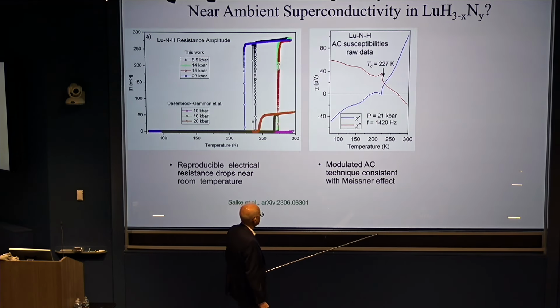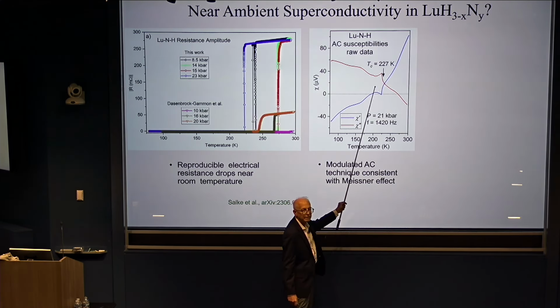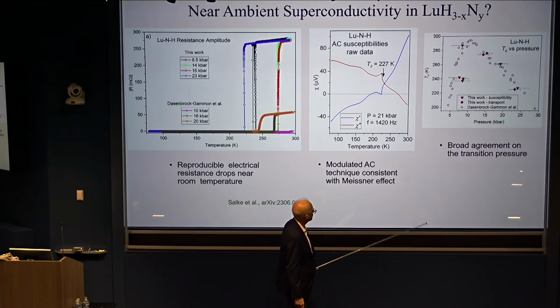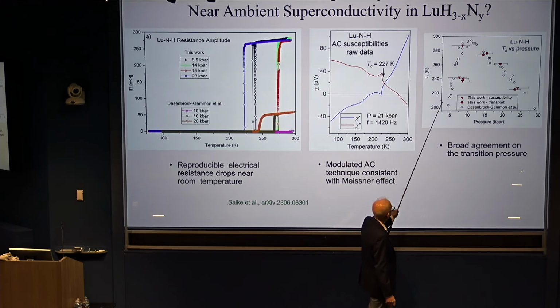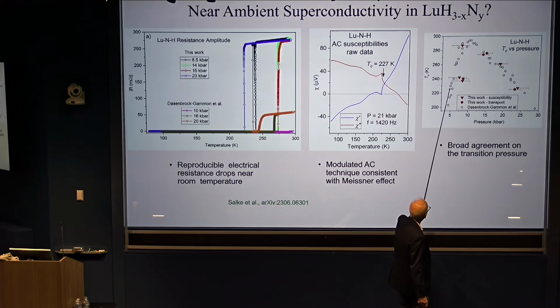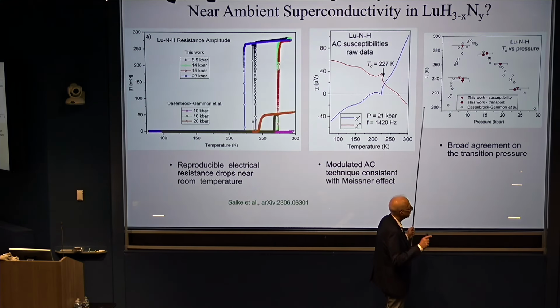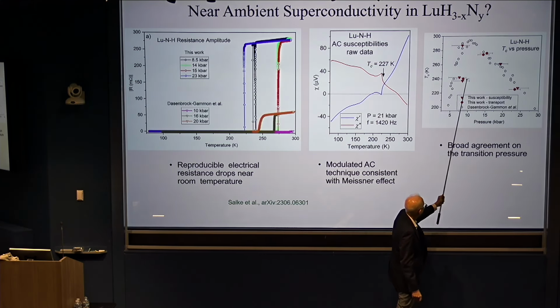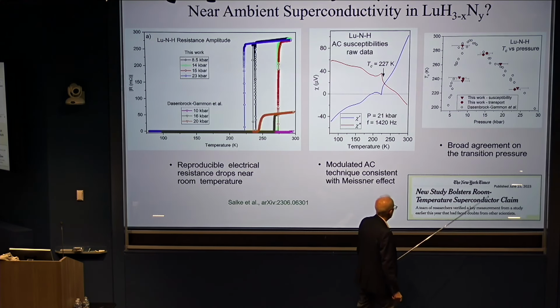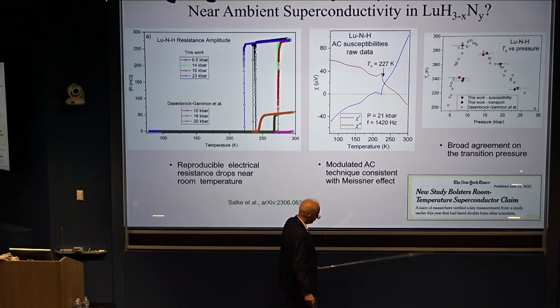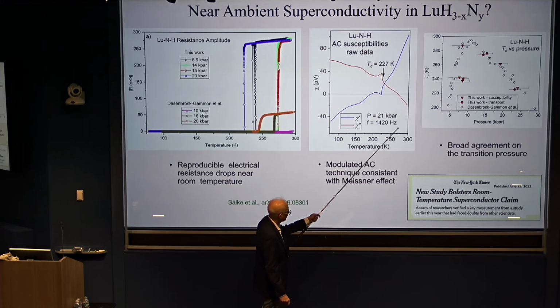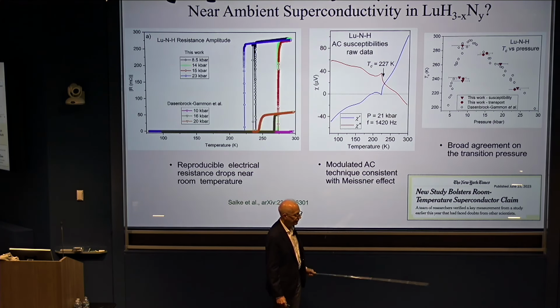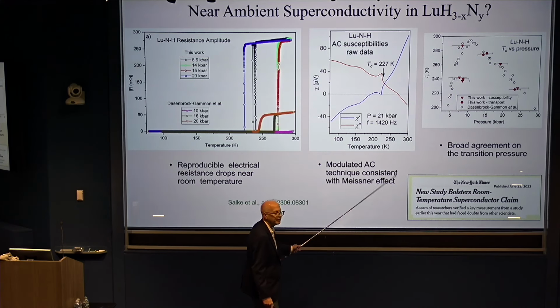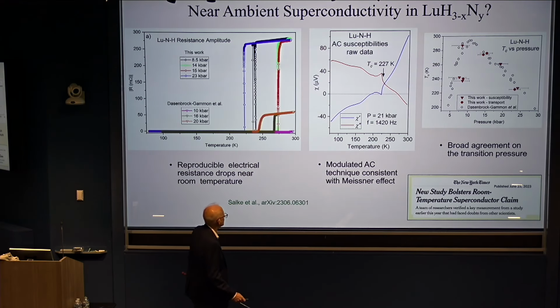We've also done magnetic susceptibility measurements, very similar to what we did for sulfur years ago, and studied a lot of other materials and see quite similar behavior. So if we plot all of this data together, we see a very similar picture of the variation in superconducting temperature, or at least some kind of critical temperature, versus pressure, now again, at quite low pressure. And this was quite exciting, and actually my students were very pleased because when we reported this online on the archive, a story appeared on the front page of the Times. So this was very nice for the CVs of my students who worked on this.